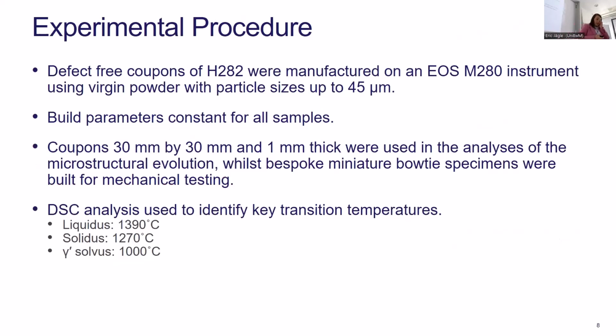So what we did, we built a bunch of Haynes 282 samples using an EOS M280 instrument from virgin powder up to sizes of 45 microns. The build parameters were kept constant for the samples, but I can't share them. Even if I wanted to, I don't actually know them. I was bound by this confidentiality again. So we had a few different coupons. So we built 30 by 30 millimeter squares by 1 millimeter thick samples that we did the microstructural characterization on. And then we had small bow tie specimens that had a 1 by 1 millimeter squared cross section by 20 millimeters sort of gauge length.